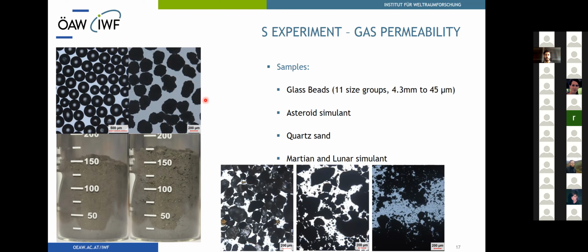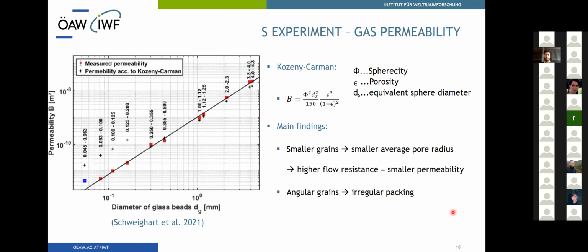Apart from glass beads, asteroid simulant, quartz sand, Martian, and lunar simulant were also analyzed. The results of this experiment are generally in agreement with other models, such as the permeability model of Kozeny-Carman. As the size of the grains gets smaller, the average pore radius also decreases, thereby increasing the resistance for the gas flow. The reason that the grains smaller than 200 micrometers deviate from this trend is related to the shape of the grains.